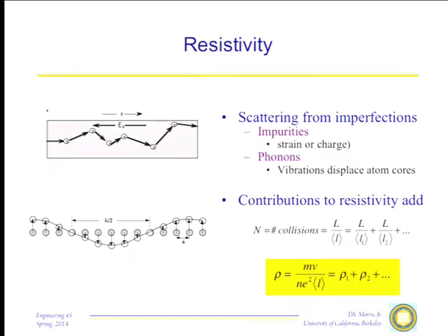The way we have set up, when you calculate the band structure of a metal, you put the electrons in states that are waves that are calculated to fit the perfect background lattice. So if we imagine we have a perfect crystal, then at zero temperature, so all of the atoms were located precisely where they were supposed to be, and if we could even ignore the zero-point vibrations, then the conductivity, the resistivity would be almost zero. Even then it wouldn't be quite zero because you have to thermally excite electrons to get them into the state, but almost zero. As you come up in temperature, the atoms begin to vibrate.